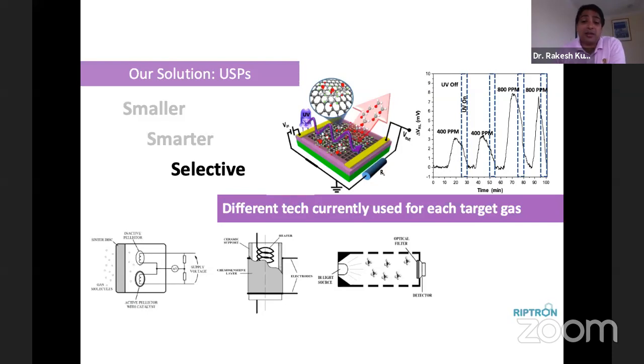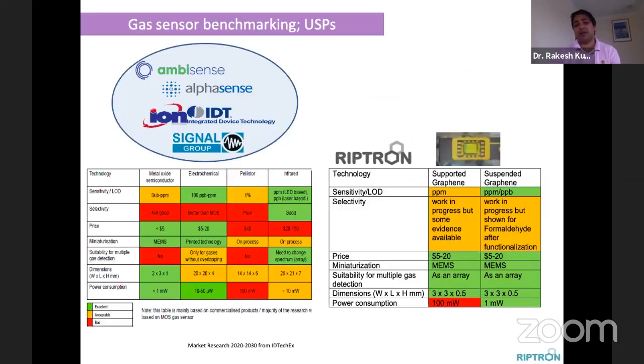And since the sensor can be easily recovered with UV irradiation, that is another advantage of the suspended graphene-based gas sensor. When we compare it with existing technologies like metal oxide-based semiconductor, electrochemical, or even infrared-based sensors, we have a few advantages. If we look at the power consumption of a metal oxide semiconductor, we need high power to generate the required temperature for operation, whereas the suspended graphene-based sensors just work at room temperature. It does not need a high temperature to detect the gas molecules.